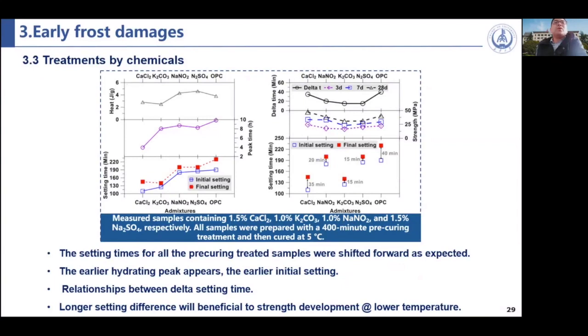And also we compared the initial setting and the final setting time in this figure with the strength development during the hydration. We cannot find a clear relationship between the initial setting and the final setting with the strength of the cement paste. However, if we compare the difference between the initial setting and the final setting, this delta time, it is similar to the strength development. So we can see the longer setting difference will be beneficial to the strength development, especially at lower temperature.